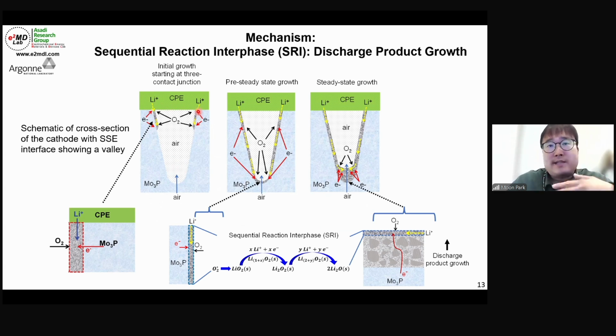So this is one unique part of the solid state electrolyte-based lithium oxygen battery. Also, as I said, we need the right, very specifically optimized condition, such that lithium conduction and electron transfer should both happen very well. Here there is a CPE electrolyte, so lithium conduction happens through the CPE, and electrons can be transferred from the Mo3P, the molybdenum phosphide coated cathode. And from this open space, the oxygen can be provided. Once the discharge of the cell starts, the discharge products start to form at this point, and then grow along the surface of the cathode.